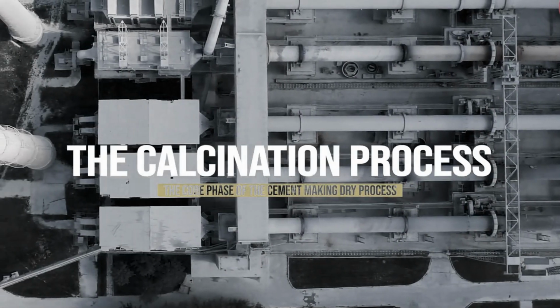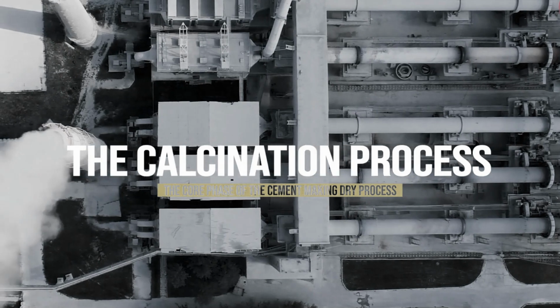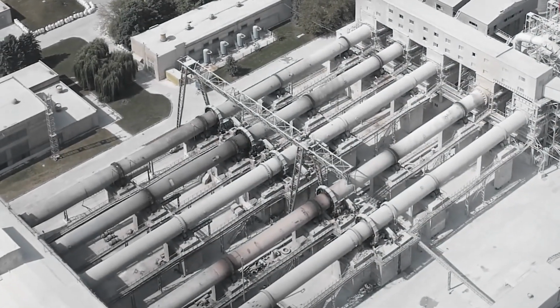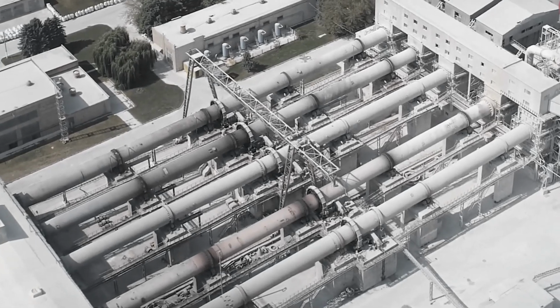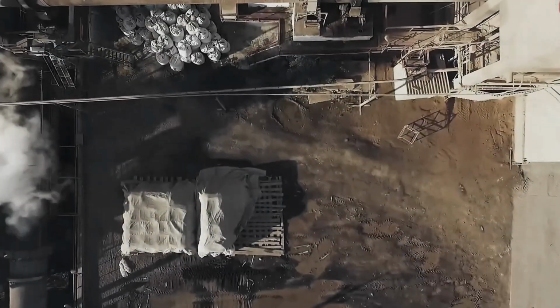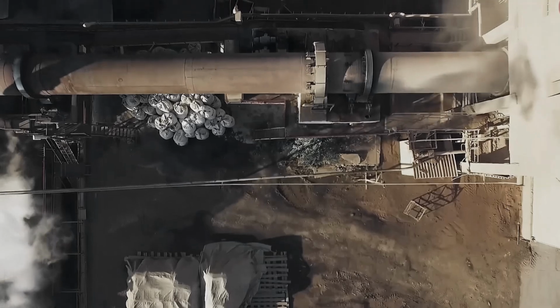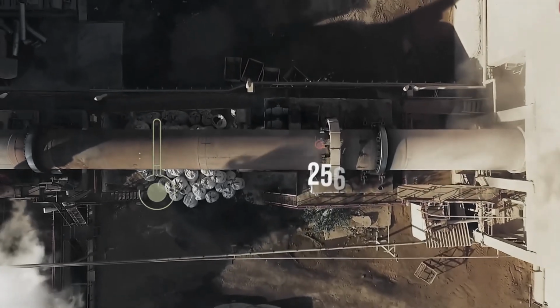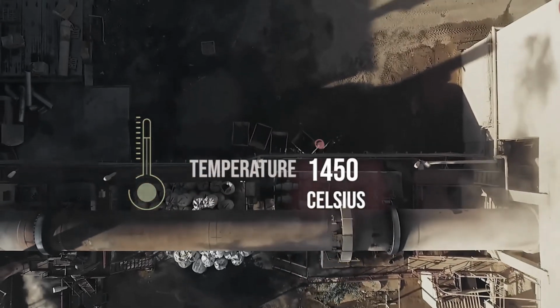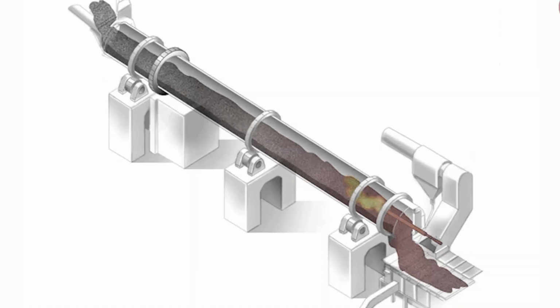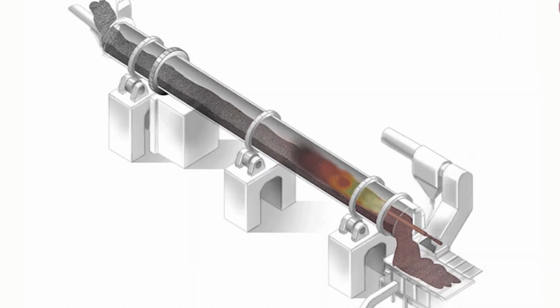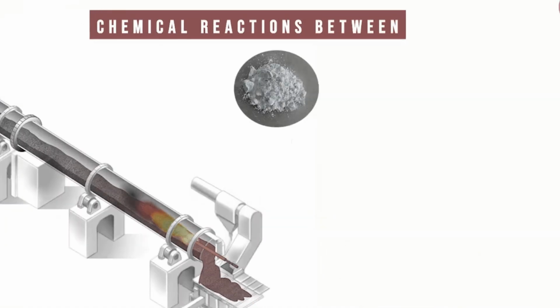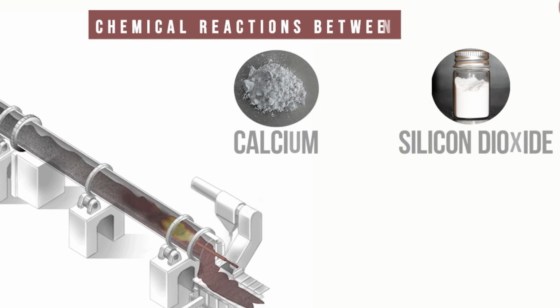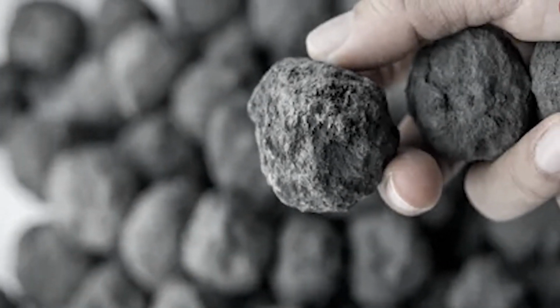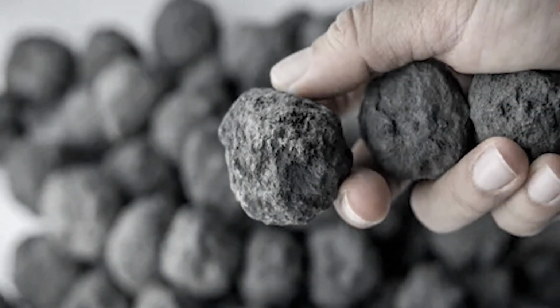Next is the calcination process, which is the core phase of the cement-making dry process. The calcination of the preheated raw meal takes place in the rotary kiln of the cement plant. The rotary kiln is a huge rotating furnace in which the raw meal is heated up to 1450 degrees Celsius and turned to clinker. The high temperature in the rotary kiln initiates a series of chemical reactions between calcium and silicon dioxide compounds, which eventually turn the raw meal into cement clinker.